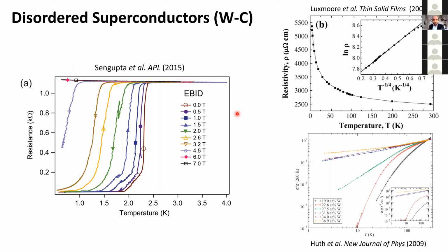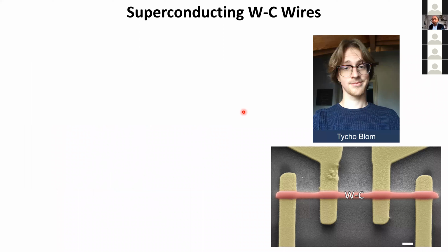we started working on this project, and of course, we were quite new to this field. And I must say that sometimes being new to a field works in your favor, because one day my bachelor student back then, Tycho, he came to me and he said he's made the superconducting tungsten carbide wire, and the transition temperature was about 2.5 Kelvin, which is great. I mean, this was already a little bit higher than the previous reports. But when we looked into it, we found out that Tycho actually had been using a much higher beam current